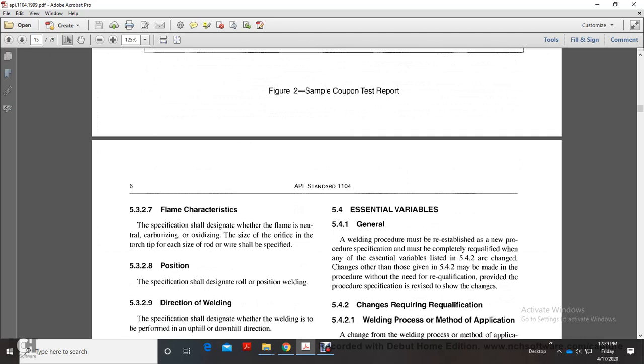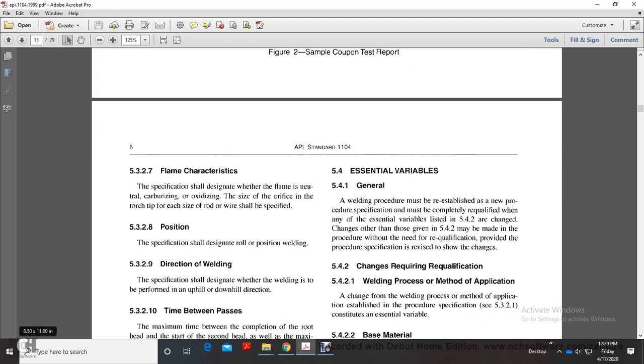Alright, 5.3.2.7 Flame characteristic. The specification shall designate whether the flame is neutral, carburizing, or oxidizing, the size of the orifice of the torch tip, and each size of the rod wire should be specified. 5.3.2.8 Position. The specification shall designate the roll or fixed position of welding. 5.3.2.9 Direction of welding. The specification shall designate whether welding is to be performed uphill or downhill.